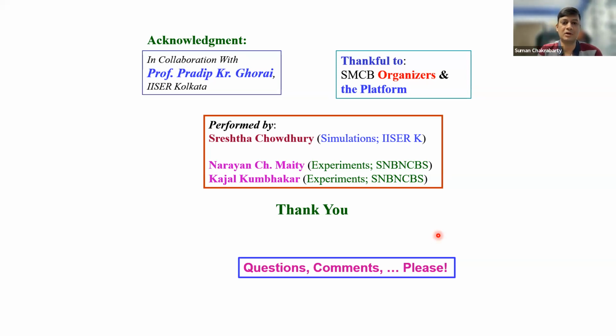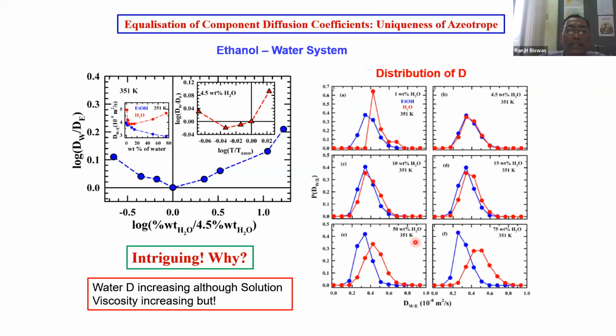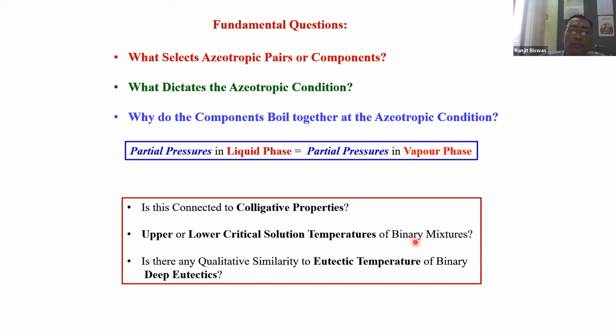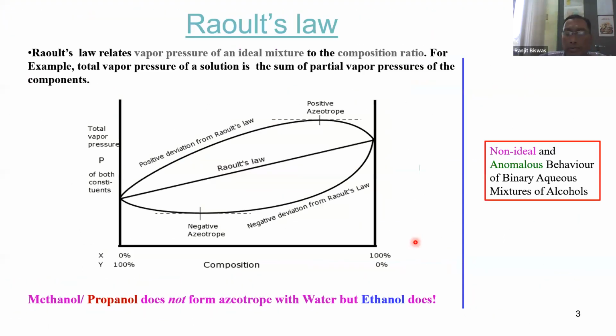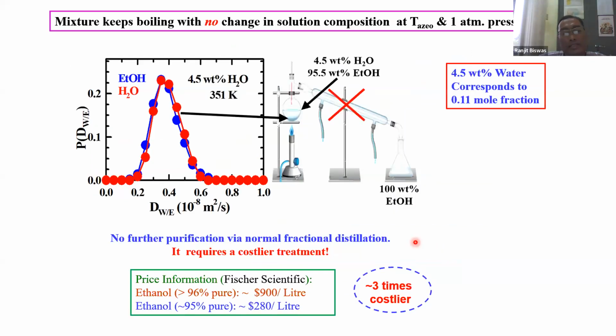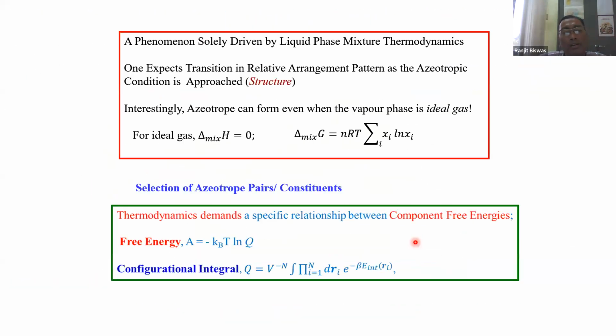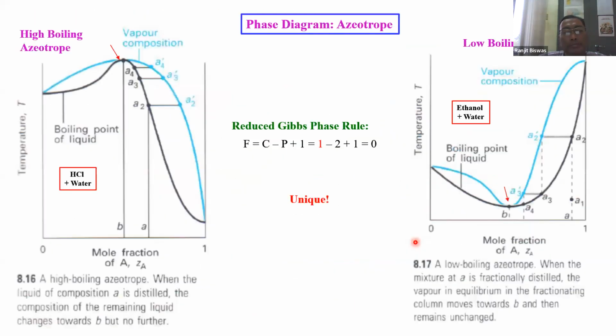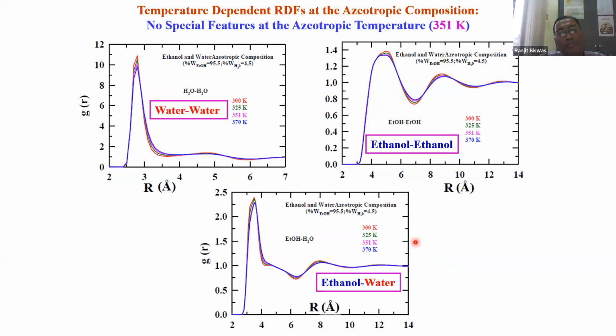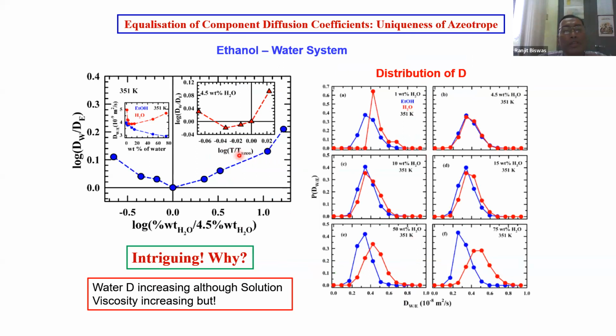How does the diffusion coefficient of water in alcohol water azeotropes vary with temperature changes? Is there a particular temperature range where diffusion is notably affected? Well, for the temperature range that we have looked at for ethanol water, we have seen the uniqueness that I have shown to you. That happened only at that temperature. There is a dependence, there is a non-monotonicity, and the dependence is different for the ethanol diffusion coefficient and the water diffusion coefficient. But that uniqueness is only at the azeotropic temperature. You can see the temperature dependence over here.